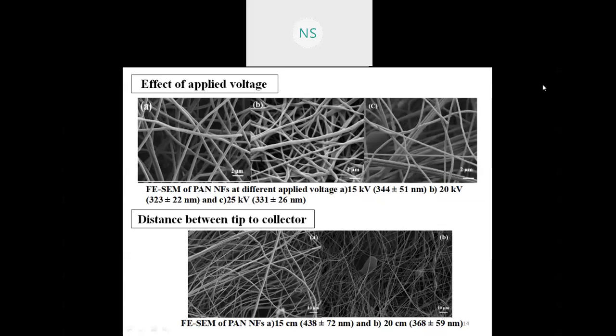When we go with the distance between the tip and the collector plate, if the distance is 15 centimeter, then 438 nanometer size of the fiber is possible, and in case of 20 centimeter, it gives 368. Means the distance between the collector plate and the tip, or we say needle, should be the maximum one, then the fiber can be stretched properly, and the size can be much lower as compared to a very small distance between the collector plate and the needle.